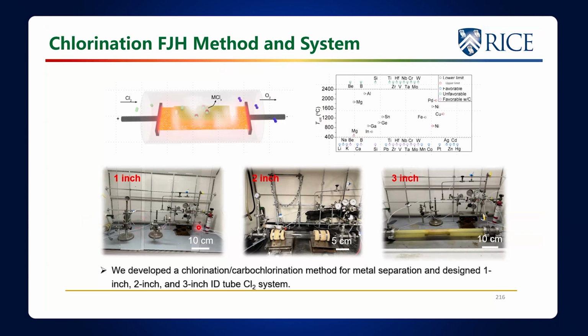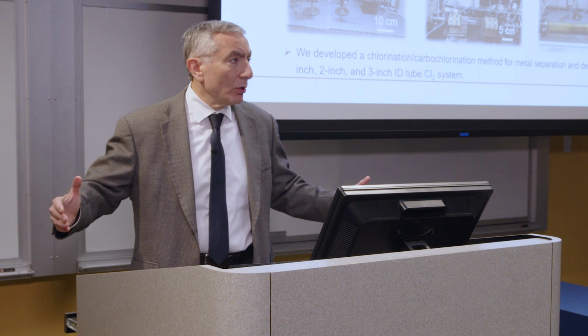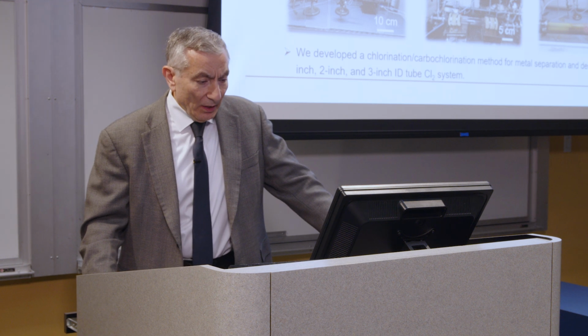So it turns out we built this 1-inch tube furnace system. There's a 1-inch tube here. Here's the chlorine cylinder that's going to end up feeding into this. So we built this in our lab. This is in a hood. And this is a 1-inch tube here. Then we had to enlarge it, because as we get up to a larger scale, we had to enlarge it. So this is now a 2-inch tube here. And then we had to go to a 3-inch tube and make these fittings at the ends, and still have the chlorine gas being able to flow in. And the hood is about 6 feet long, and this fills up just about the whole hood. So it shows you what happens here.